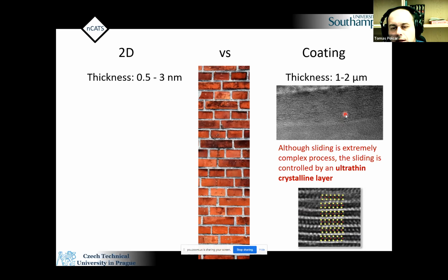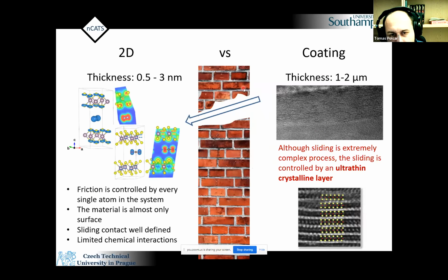So I have two questions now to answer. One, how can this happen? Why does this material form this tribo layer from almost anything we prepare? We always got the same thing. We always got this tribo layer. This is the first question. And second question, of course, if this is my sliding interface, I can ignore all that is above and below, and I can just study the sliding of these materials, which simplifies my problem extremely, because this I can now access by molecular dynamics or ab initio, by basically nanoscale simulations. So I now have a way to really go back to these 2D materials, and this is what I will start to describe in a little bit of detail now.